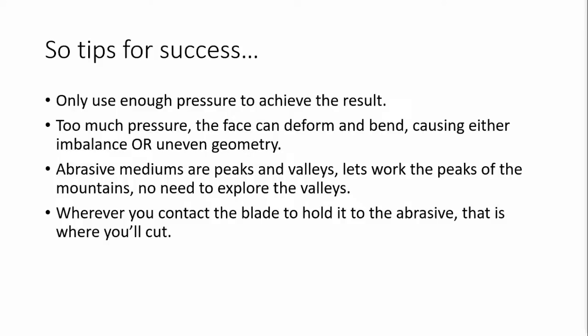Also, your abrasive mediums, whether it's sandpaper or silicon carbide or aluminum oxide powders, or a wet stone, natural stone, Arkansas stone, concrete, cinder block, the surface of that abrasive medium under a microscope looks like tiny little mountains of cutting grain. When you press too hard into an abrasive medium, you're trying to explore the valleys of that abrasive, when we really should be exploring the tops. The reason why abrasive grains cut is because of the sharp pointed tops of those mountains and the edges of those mountains. So if I don't use as much pressure, one, I'm not going to wear out my stone or sandpaper or other medium as quickly, but also I can control how aggressively that abrasive medium cuts into the tool.